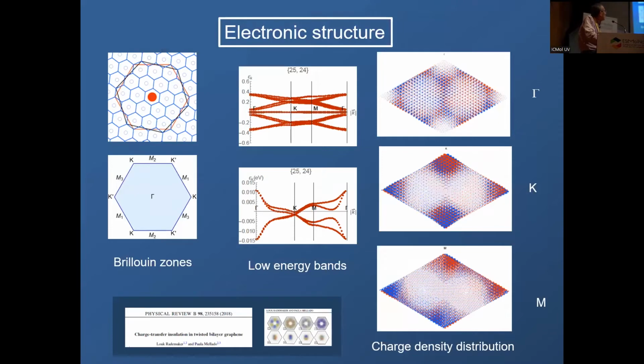These are early calculations we did, and let's see if this is this famous flat band, which is scaled up here. And it's also remarkable because there are flat bands in the cuprates and in the heavy fermion systems, of course. But you have here a large unit cell, and interestingly, depending where in the flat band you are, the charge distribution is very different. For instance, in the heavy fermion systems, which contain elements like cerium or uranium, there are flat bands, but these flat bands are basically located in f orbitals in these elements, and they are flat because they interact very little with similar f orbitals in other unit cells, but the bands are always pinned to the f orbitals. Here, there's no orbitals to pin these flat bands.